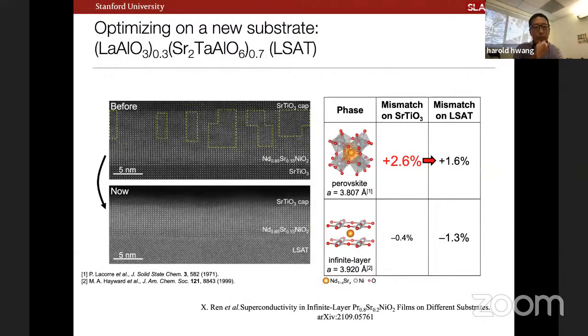And so we've been trying to work on moving to a new substrate, colloquially known as LSAT. It's a little bit complicated. The point is as follows. Everything I showed you so far was on strontium titanate. And it's really this question of how do you balance the competing materials aspects at play. So you can grow the perovskite phase under large tensile strain. And then if you reduce that to the infinite layer phase, it should be, in principle, fairly close in lattice match to what it would ideally want to be. But you pay a price of these extended defects, as I just alluded to.